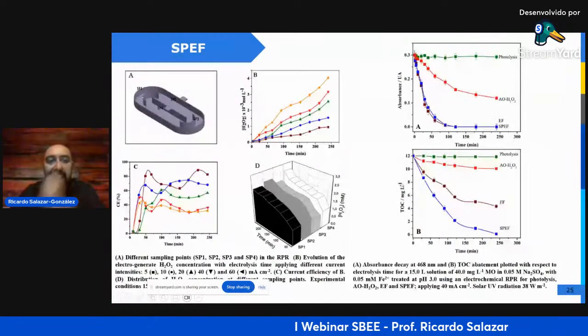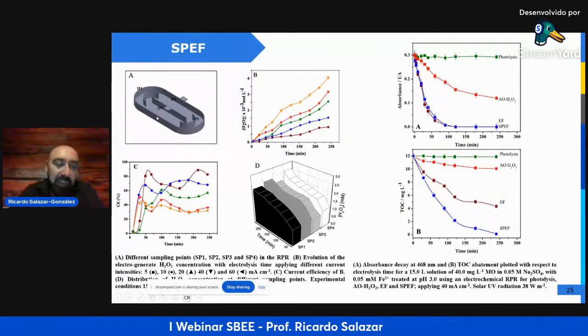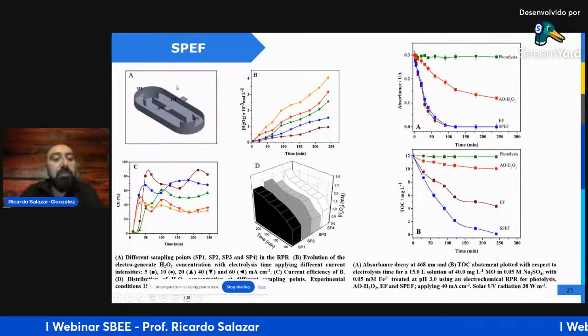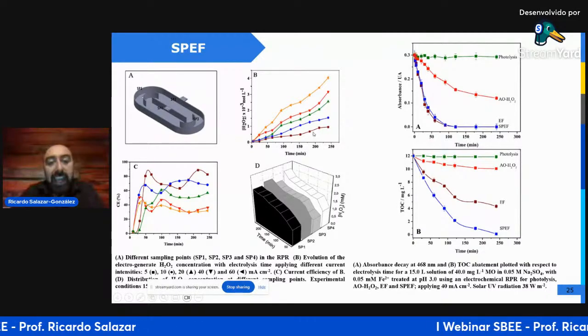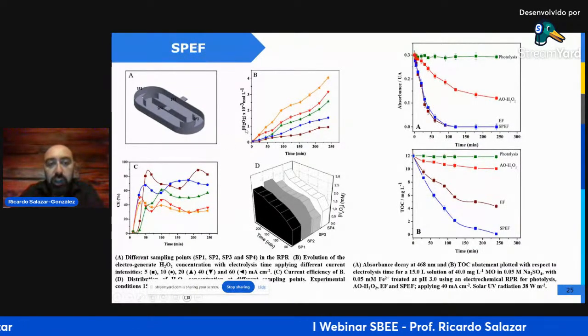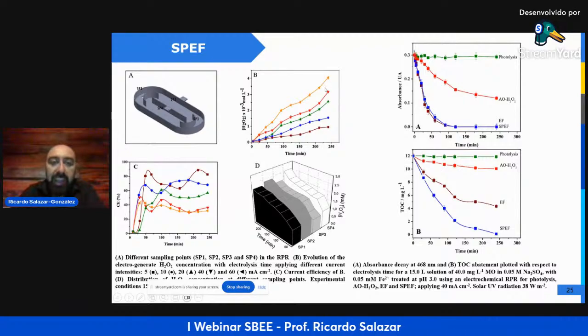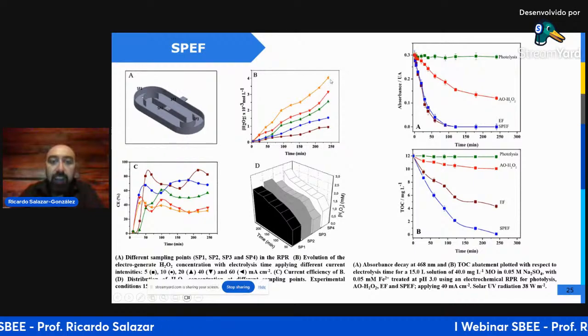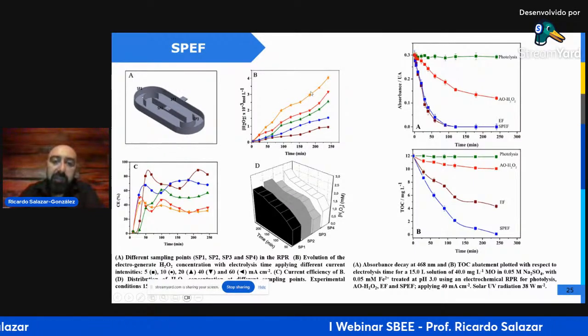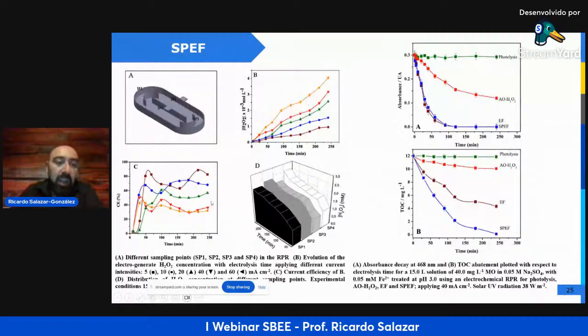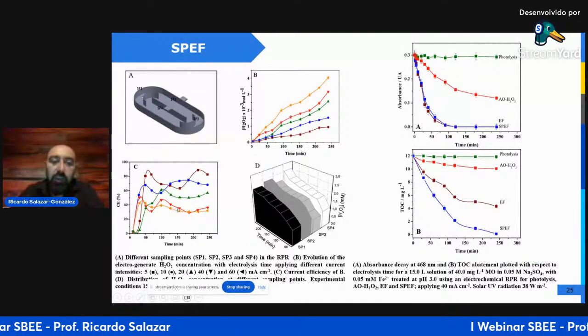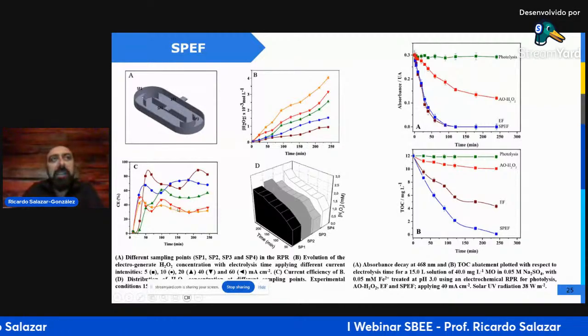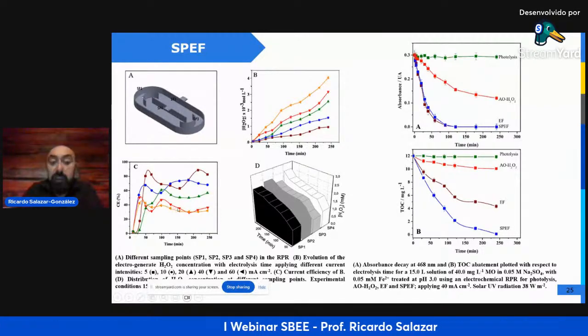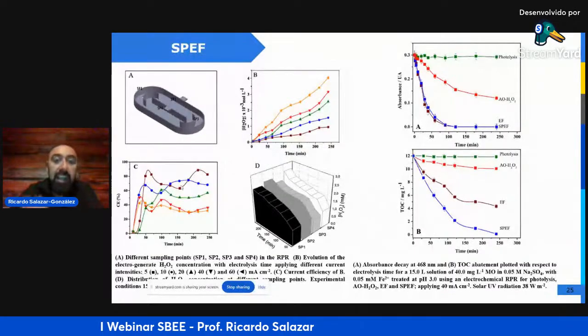When we study the hydrogen peroxide production, you can see that the concentration of peroxide increased with the applied current density. If we have a high current density applied, we observe a higher concentration of peroxide with very good efficiency. In this kind of process, if we have more than 30% or 40% efficiency in the production of hydrogen peroxide, it's a good efficiency.